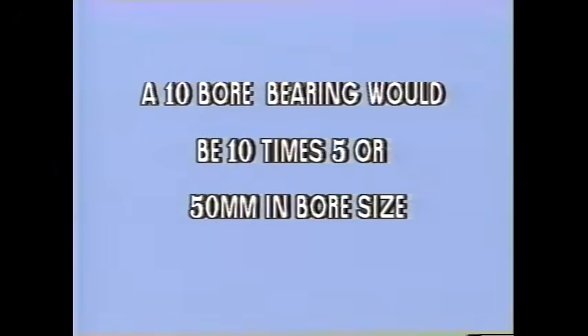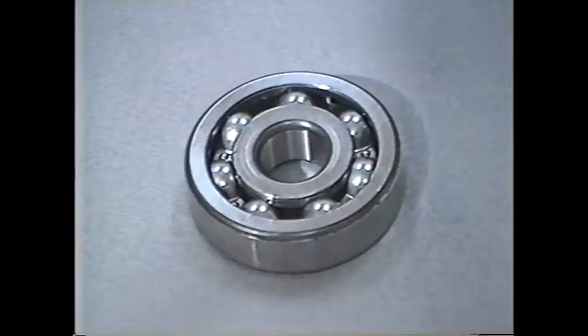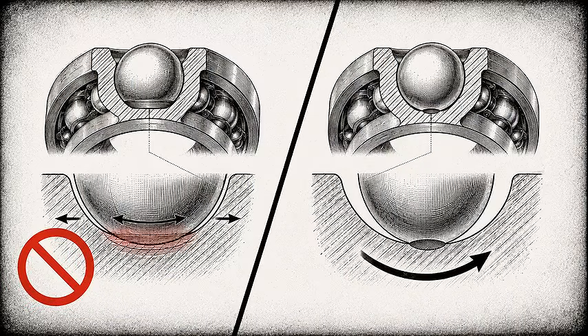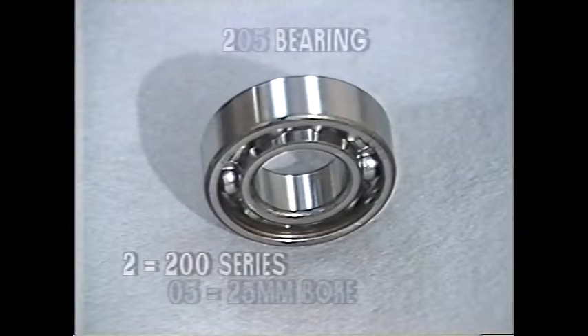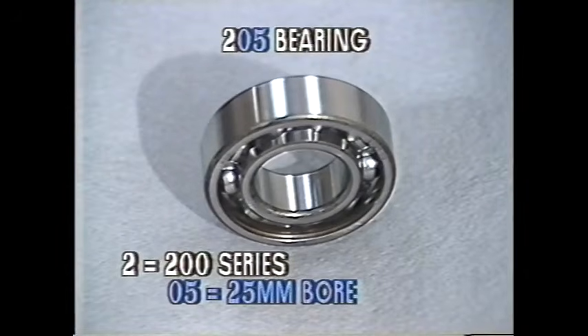The balls are only half the problem. The rings they roll in are the other half, and they contain a subtlety that repays attention. Instinct says that the groove in the raceway should match the ball exactly, cradling it. Instinct is wrong, and dangerously so. If the groove radius equaled the ball radius, the ball would contact the raceway along a broad curved band, rather than at a point. And because different parts of that band would sit at different distances from the bearing's axis, they would need to travel at different speeds. They cannot, it is one rigid ball.